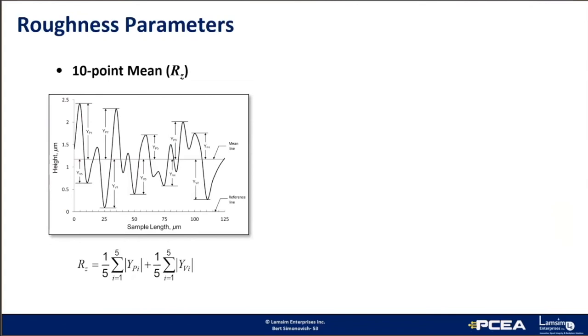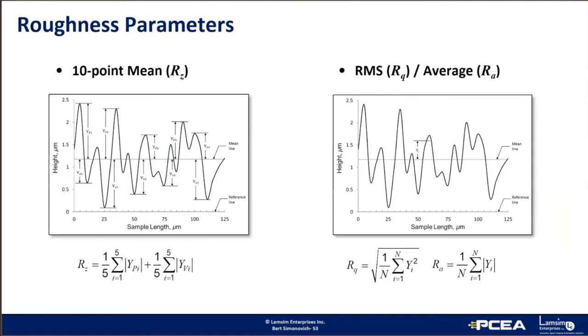Typical roughness parameters found on data sheets are shown here. The 10-point mean roughness, RZ, is the most common for the treated side of the foil. It's the sum of the average of the 5 highest peaks and the 5 lowest valleys of the measured roughness profile over the sample length. But sometimes average roughness, RA, is reported for the drum side, and RMS roughness, RQ, may or may not be reported. In my experience, I found there's much confusion in the industry, depending on who you talk to or literature that you read. Often, marketing FAEs will report RZ numbers as RMS roughness. And in literature or even websites, RA and RQ often get mistyped because the A and the Q fonts are similar. And that's why I always like to go to the foil manufacturer's data sheet to get the right numbers.